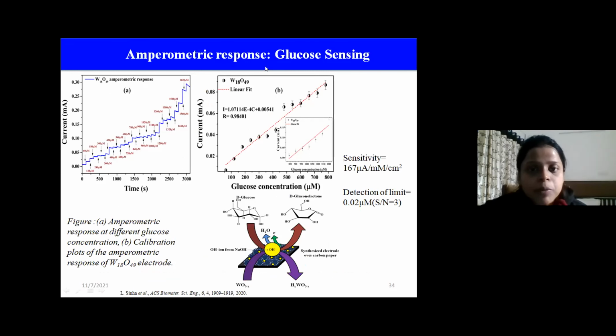Now this is the amperometric response of glucose sensing, and here we are seeing that by successively adding 60 micromolar of glucose, the material is giving a continuous enhancement in current till 2 millimolar, and the linearity is also maintained with an R squared of 0.98401. So the sensitivity has been calculated at 167 microampere per millimolar centimeter square with a very low detection limit of